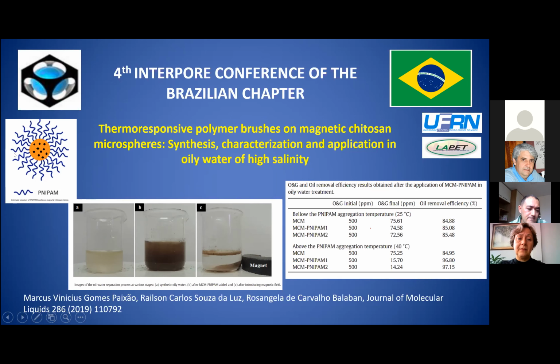In this scheme, we have the core made of chitosan, cross-linked chitosan. Inside the core, you have some magnetic particles of iron oxide. And on the surface of the microspheres, we have a thermosensible polymer, synthetic polymer. So these brushes are made of poly N-isopropylacrylamide. What happened?